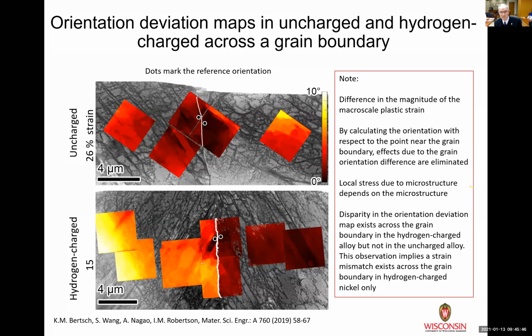The white line that you see roughly in the center indicates a grain boundary. The black dots with the white borders, those are our reference points. And we take a reference point so we don't have to worry about the misorientation difference as you go across a grain boundary. That's been neutralized by taking these reference points. What do you see? If I look at the two sets of images, I notice that in the upper one, there's no real strain mismatch or misorientation mismatch because it's a dark red, a light red on both sides of the grain boundary.